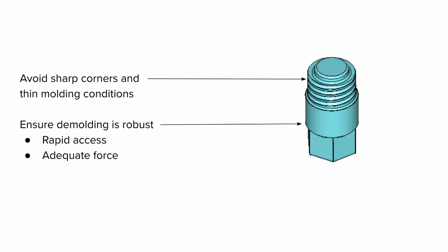So additional considerations. This core is of great interest. Avoid sharp corners and thin molding conditions. One of the questions in the Q&A was regarding thermal transfer, and naturally a printed mold set doesn't draw the heat out at the same speed that metallics will. So when we printed the cores for this mold, we printed 6 cores, and we would alternate between the cores as we were molding to keep the cores as cool as possible. That helps to a great degree, but towards the end of the sample, we were increasing pressures to see what the stack would handle. Eventually, the thin corners up on the top, when we would demold this core, they were breaking off. It just couldn't handle a demolding circumstance like that.